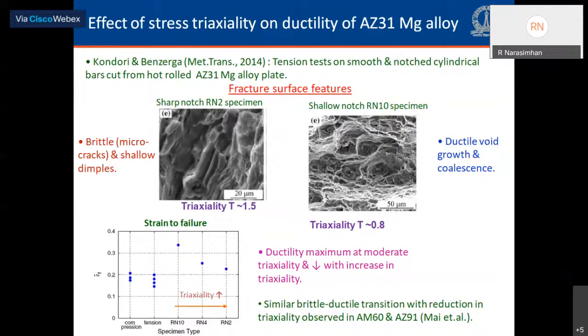which has got a triaxiality. The triaxiality T is defined here as the ratio of the mean stress to the equivalent stress, sigma m by sigma e. So the Rn2 specimen has a triaxiality of around 1.5. And if you examine the fracture surface, you can see that there are some grooves or flutes, elongated groove-like features, which are associated with the cleavage type mechanism, basically twin-induced microcracks.